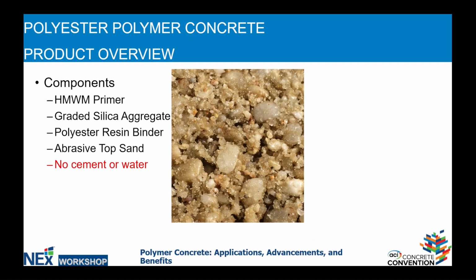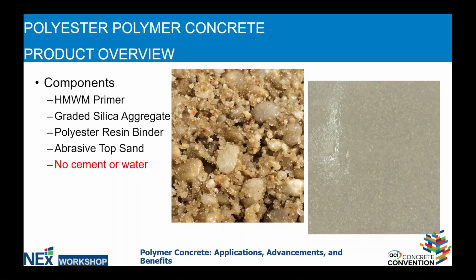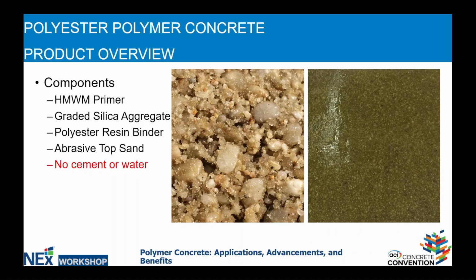The components of the system will include a high molecular weight methacrylate primer, which can be adjusted based on the temperature conditions in the field, substrate temperature being the driver. You know, anything from down to 40 degrees up to 100 degrees is possible to install these types of systems. The polyester concrete itself is a combination of graded silica aggregates, a polyester resin binder, and an abrasive top sand, which gives the surface texture and slip resistance. In this example, the combination of components and ingredients contains no cement, no Portland cement, and no water.